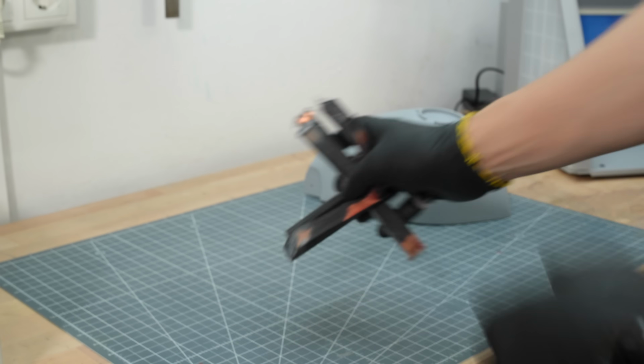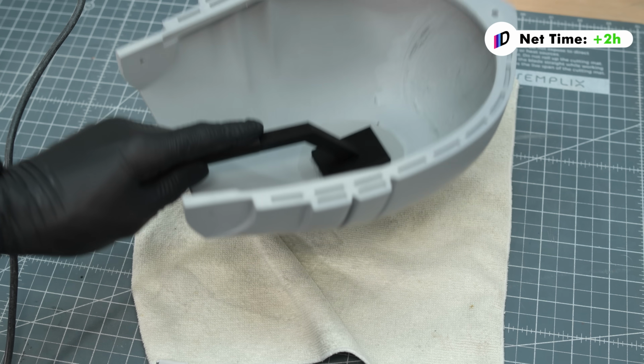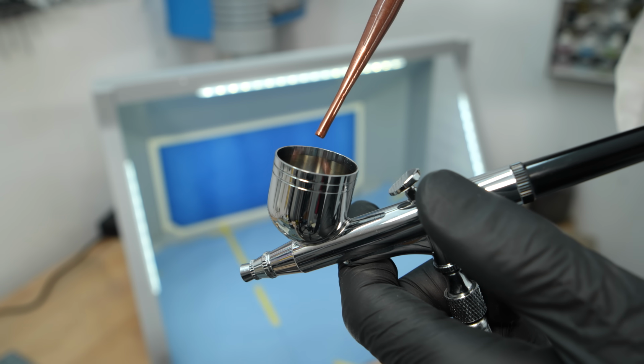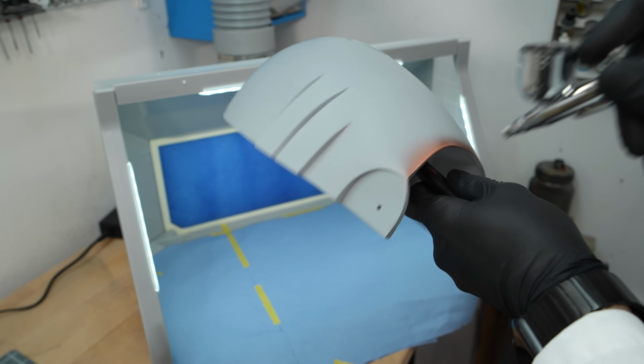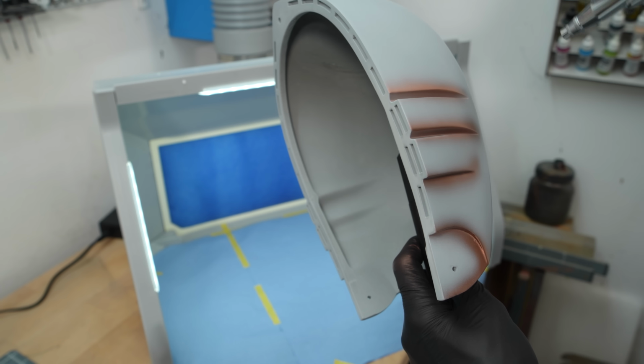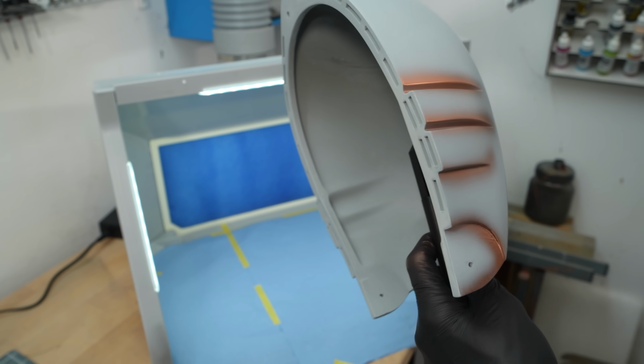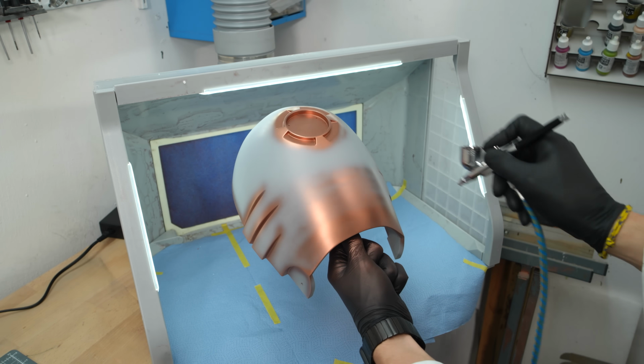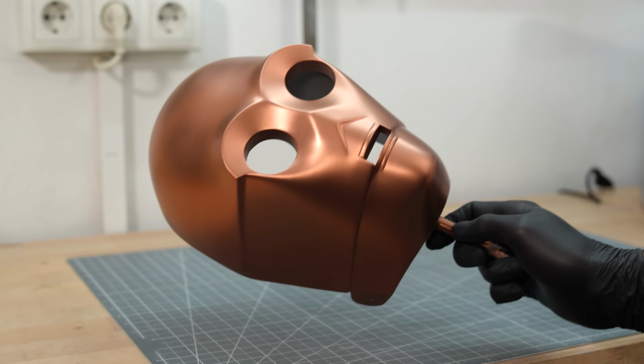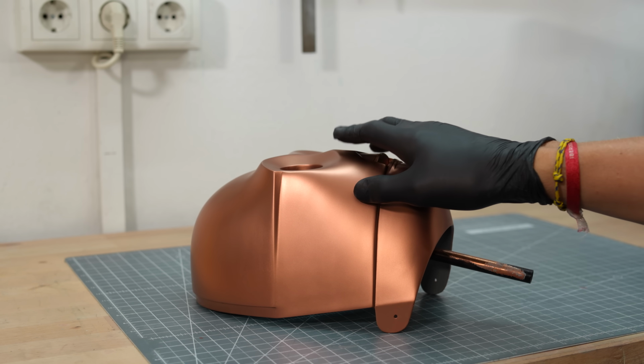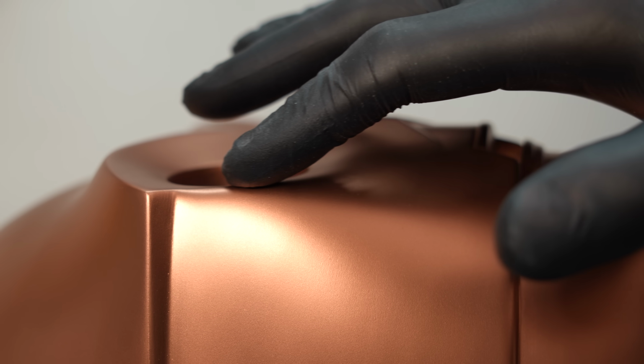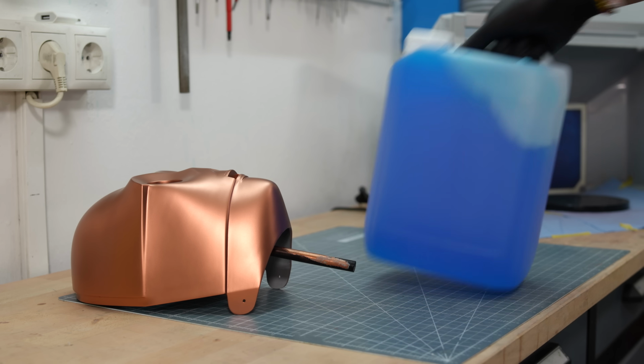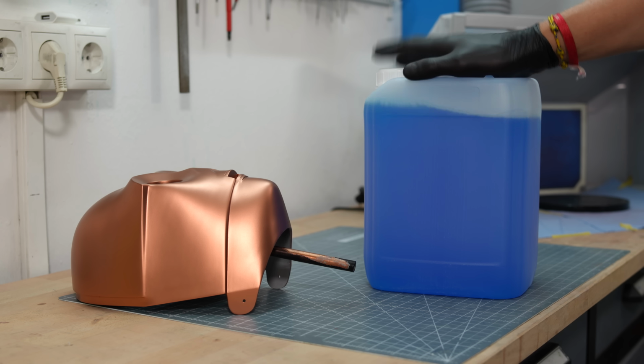To better grip the large parts, I printed some holders and fixed them with hot glue. I try to work evenly and spray on a thick, smooth layer. I use around 2 bar for this. Let it dry thoroughly and, if necessary, gently smooth it out with a brush. Gently.